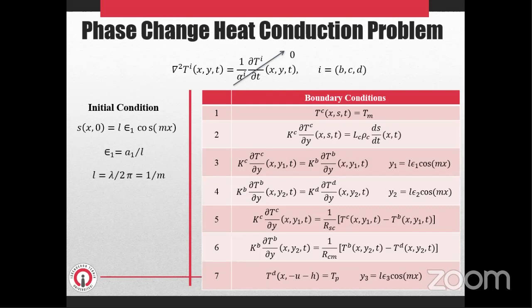Due to the nonlinearity of the governing equations, an exact analytic solution is found for some limiting cases only. In this work, the thermal diffusivities of the materials are assumed to be infinitely large, and this assumption allows us to solve this heat conduction problem analytically, since the Fourier-type heat conduction differential equation is transformed to Laplacian type. The initial condition denotes a very hot solidified shell on the coating surface at initial time. Epsilon 1 denotes the aspect ratio of the upper surface of the coating. Similarly, the same aspect ratios are defined for both surfaces of the mold.